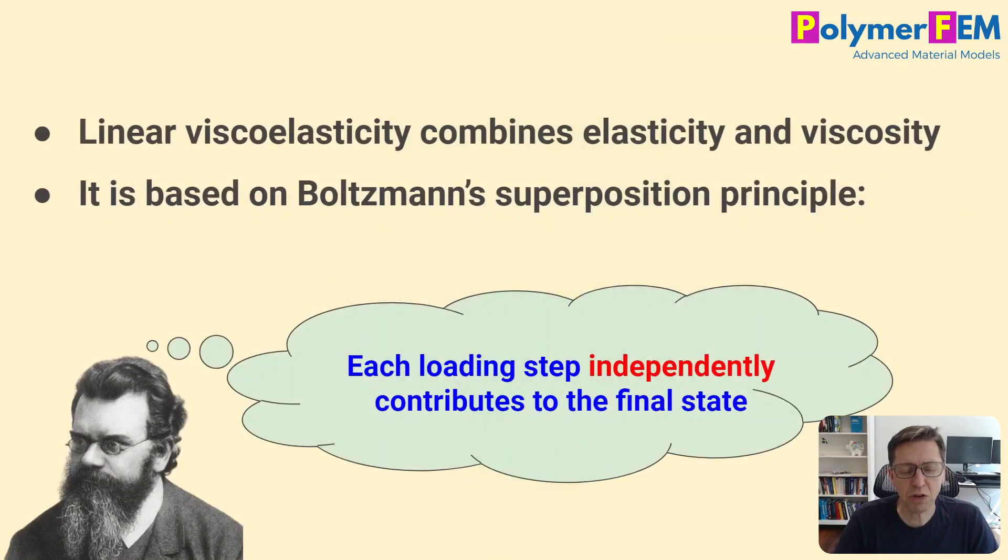And there is one very good way to determine that. And that comes back to the definition of linear viscoelasticity, which is based on Boltzmann's superposition principle. So Boltzmann said that each loading step makes an independent contribution to the final state. And that's the foundation of linear viscoelasticity. We can use this definition to come up with specific experiments to directly tell us if a material will behave in a linear viscoelastic way or not.